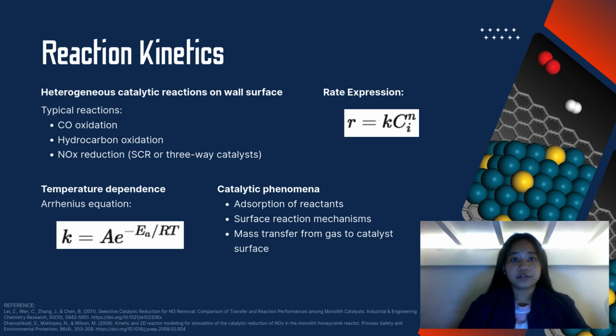Reaction kinetics. The most important part of the model is the catalytic reaction kinetics. In emission control systems, pollutants are converted through heterogeneous catalysis, occurring on the catalyst coating inside the monolith channels. Typical reactions include oxidation of carbon monoxide and hydrocarbons as well as the reduction of nitrogen oxides. The reaction rates are usually expressed using Arrhenius type equations, which relate the reaction rate to temperature and reactant concentration. The simulation must also account for adsorption and desorption on catalyst surfaces and diffusion from the gas phase to the catalytic wall, which strongly influence overall conversion.